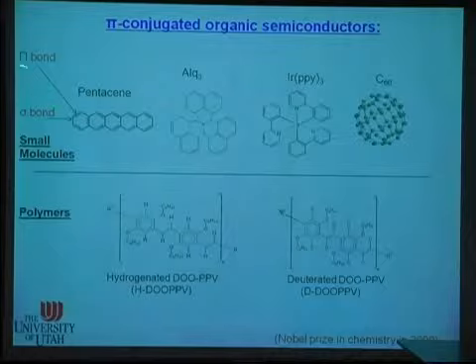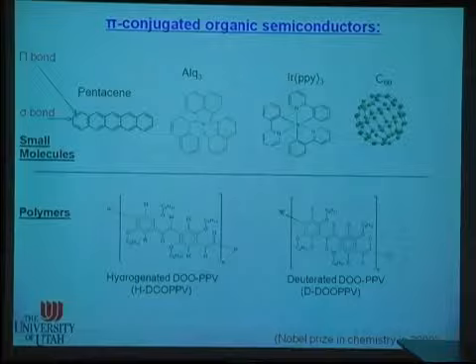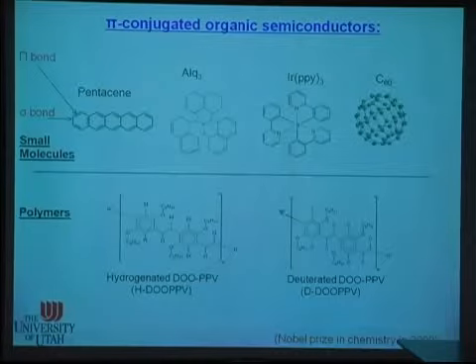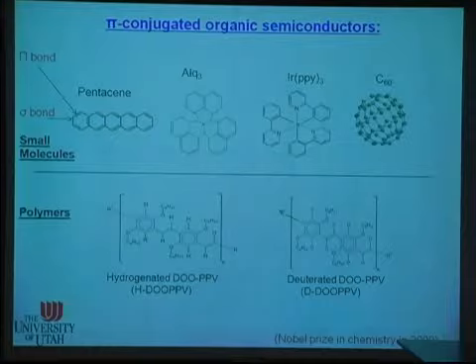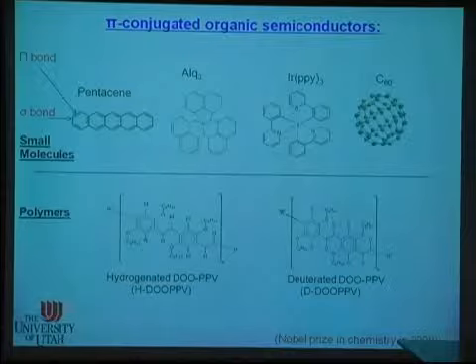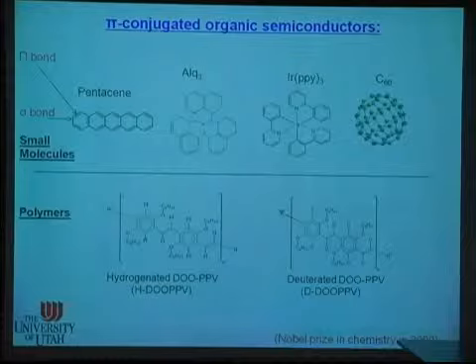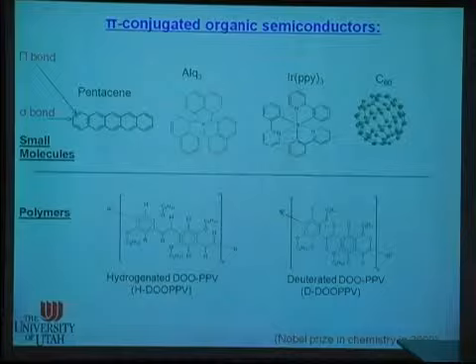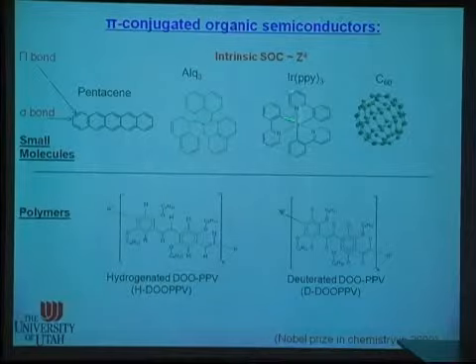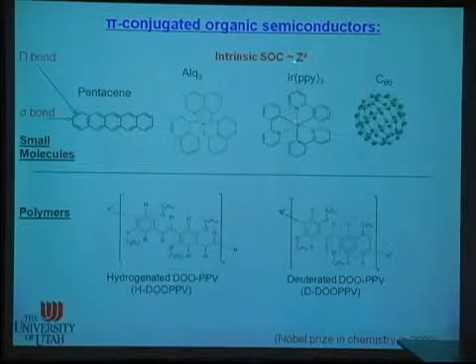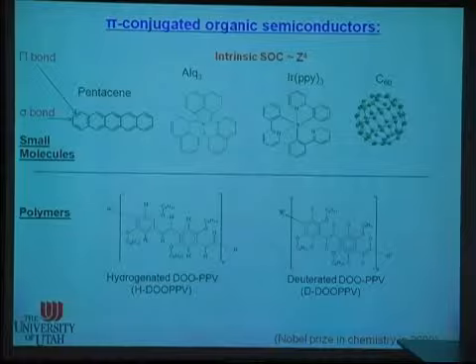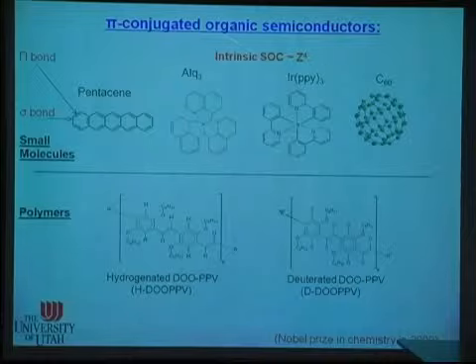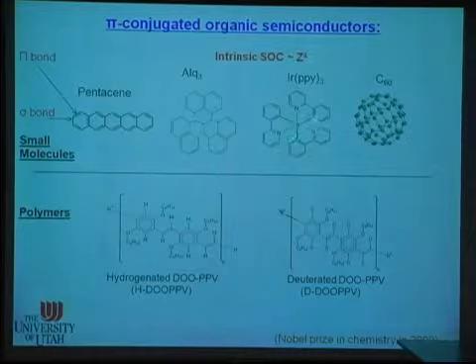But the double bond here includes one sigma bond and one pi bond. And the electrons in the pi bonds can be delocalized in order to form the electronic properties of those materials. You can see all of those materials have double bonds, which means they have pi electrons. The interesting point in organic materials is that you can engineer the spin-spin interaction, like the hyperfine interaction or spin-orbit coupling. In those materials, Ir(ppy)3 here has the iridium heavy metal inside the small molecule. So the spin-orbit coupling is very large because the intrinsic spin-orbit coupling goes like the number of protons to the fourth.